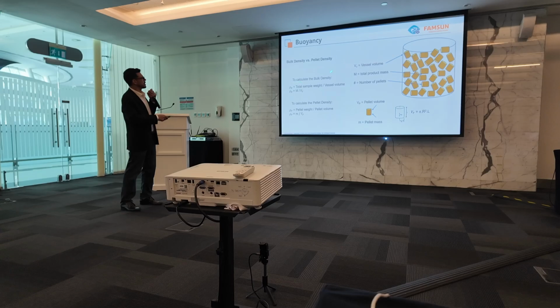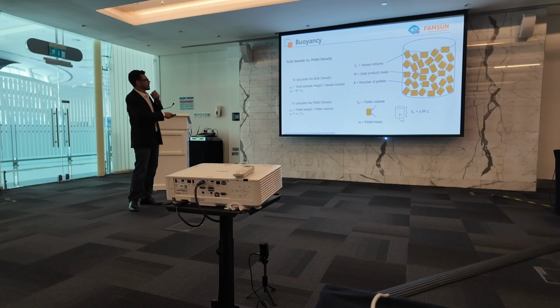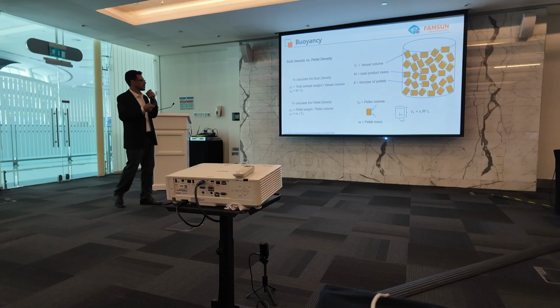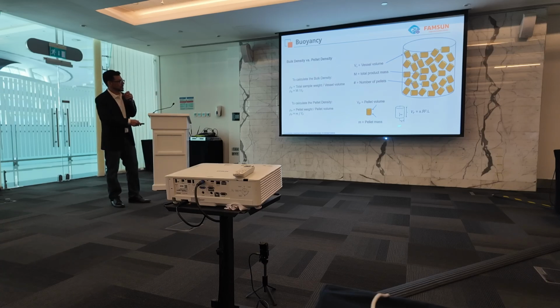So how do we calculate the bulk density? It's very simple. We have a sample, we have a vessel volume, we measure the sample weight, and then we just divide the weight by the vessel volume. We can calculate the bulk density. This is normal. This is not so common to be done. This is the pellet density.